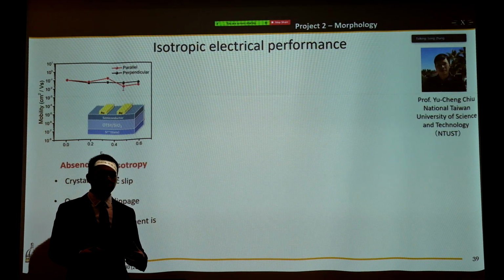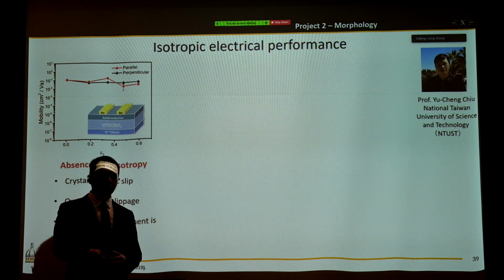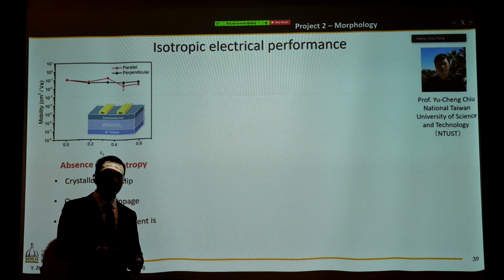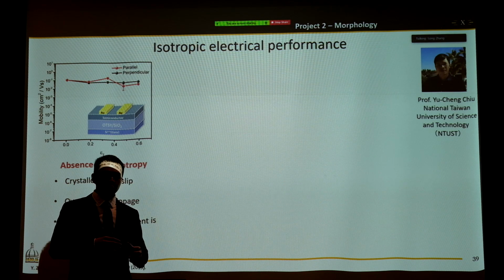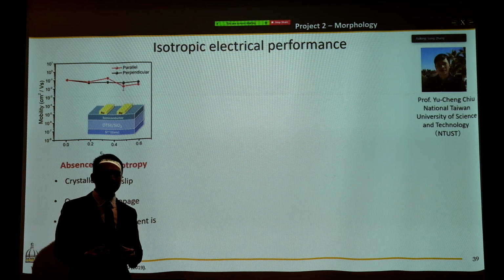So now you might wonder, what's going to be the effect of this morphological transition on the thin film electrical performance? Our collaborator, Prof. Yu-Cheng Chiu from NTUST, helped us perform this kind of measurement by fabricating OFET devices. As you can see here, along the charge transport direction versus perpendicular to it, we do not see any difference in the mobility value under strain. This means the charge transport is as efficient as the non-strain state.